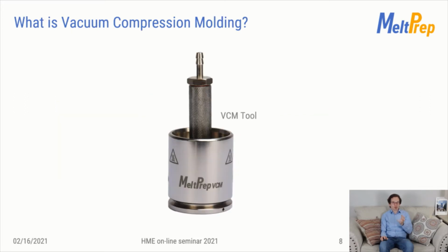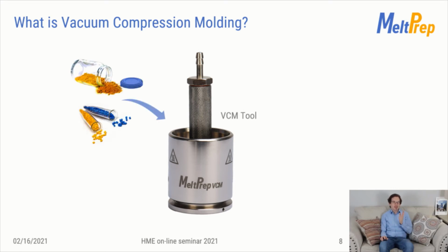Let me show you how it works. This here is the VCM tool. The vacuum compression molding process transforms any thermoplastic powder into a solid specimen with defined dimensions. Parallel surfaces, no air or moisture inclusions, and the best of it, it works lossless. Put 1 gram of material in on one side, and after processing, you will get 1 gram of material out. There are no losses.